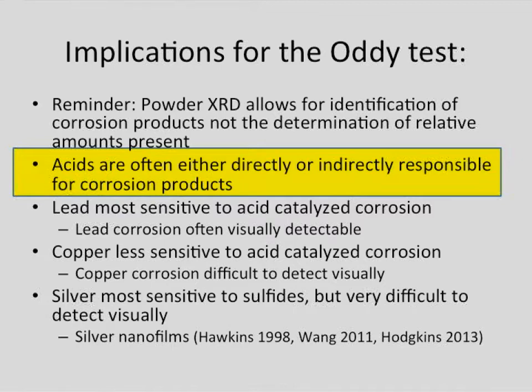And I find that the copper and the silver are difficult to assess visually. For that, people have started looking at silver, and I think people even looked at copper thin films, which end up having more topography, and color change on the surface ends up being a little bit more exacerbated, so you can see changes more easily.